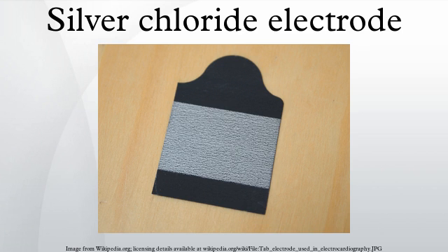Commercial reference electrodes consist of a plastic tube electrode body. The electrode is a silver wire coated with a thin layer of silver chloride, either physically by dipping the wire in molten silver chloride, or chemically by electroplating the wire in concentrated hydrochloric acid. A porous plug on one end allows contact between the field environment and a silver chloride electrolyte. An insulated lead wire connects the silver rod with measuring instruments. A voltmeter negative lead is connected to the test wire. The reference electrode contains potassium chloride to stabilize the silver chloride concentration.